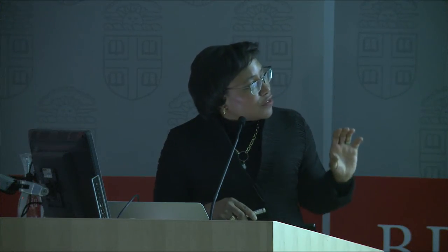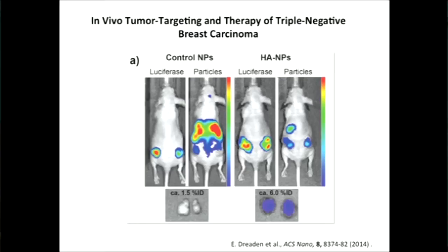On the other hand, if you look at the hyaluronic acid LBL systems, we can see a meaningful difference. We still get something in the tumor, in the liver, and this is a common issue with nanoparticle delivery. But we see that there's a much greater amount that has accumulated in the tumor.